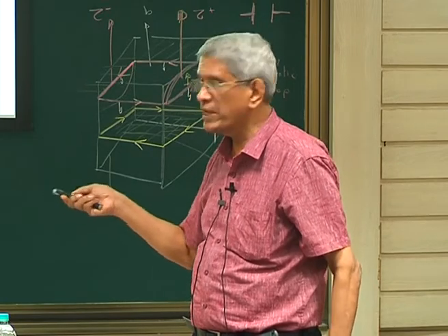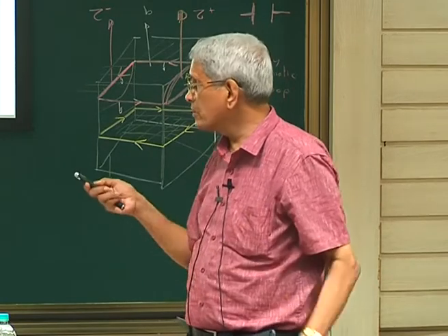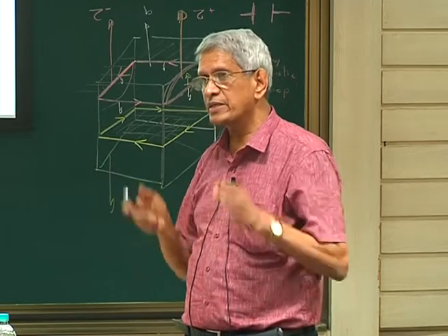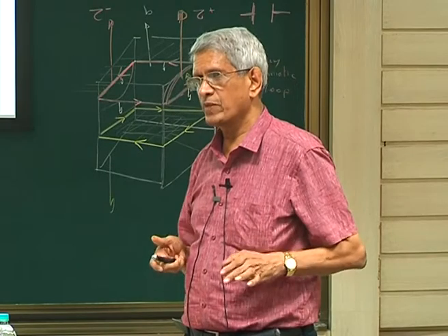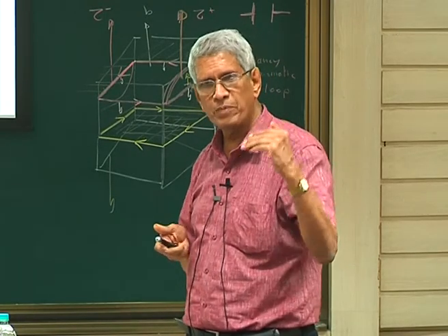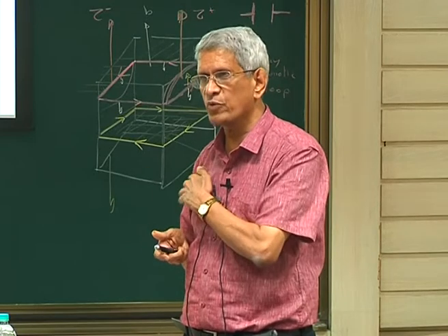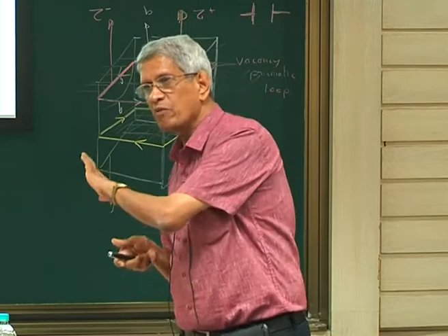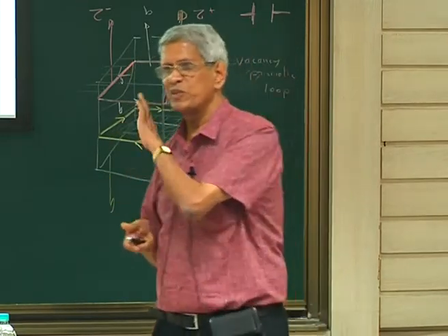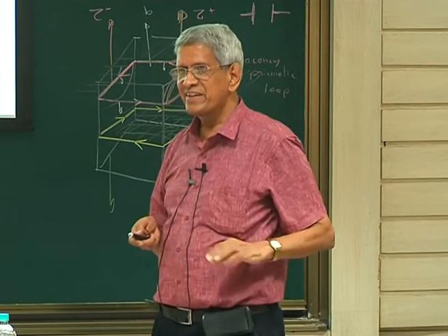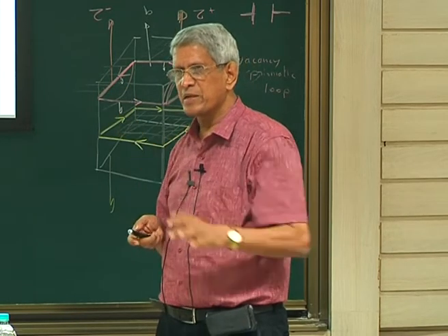You see that in the same direction the beam is coming. Similarly, from this direction again, so multiple scattering is taking place in the material. Whereas when we do an X-ray diffraction, we assume that when the X-ray beam enters into the sample and comes out of it, it's only a single scattering event. The theory developed on quantitative imaging using that is called kinematical. The one which is taken using this is called dynamical.